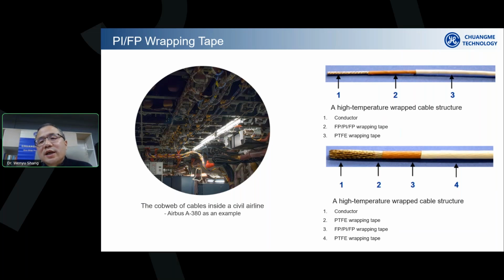So basically, it is installed on the wire. As I said, you wrap the tape at a certain angle, with the adjacent two cycles overlapping each other on the cable. And then after the cable is made, like this structure, the whole cable is put through an oven with a temperature between 350 degrees C and 400 degrees C, to make the second layer a fully continuous and non-cracking insulation layer to offer the high temperature resistance performance.